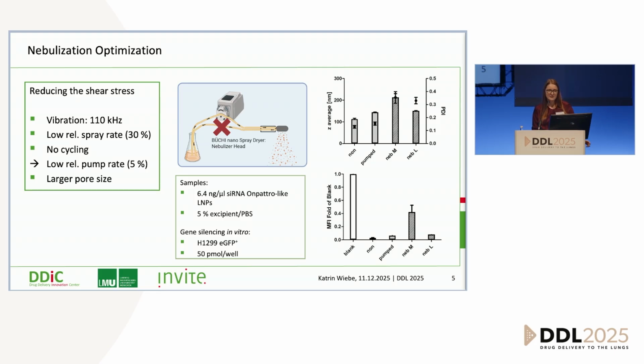The last thing we had to think about was the pore size. And for this device, we have different pore sizes available. If you have a look at the nebulized particles, nebulized with a medium-sized pores, then you see that the size increases a lot, and also we lose a lot of function in the cells. However, if we use the larger mesh, we can see that there is not a lot of size increase, and they work pretty well. So the nebulization we have optimized, and this works quite okay.